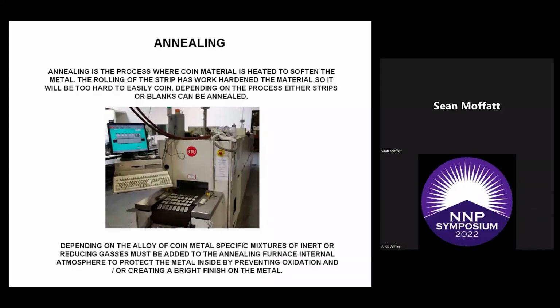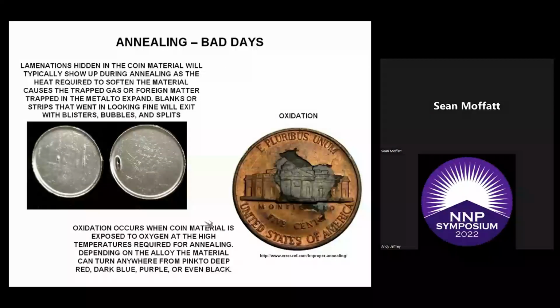All right, now depending on the process, you can either anneal your strips or the blanks can be annealed, depending on what you want. Now, depending on the alloy of the coin material, specific mixtures of an inert or what's known as a reducing gas must be added to the annealing furnace internal atmosphere to protect the metal inside by preventing oxidation and or creating a bright finish on the metal. Most commonly what's used is a nitrogen and hydrogen mix. The nitrogen pushes out any of the oxygen and the hydrogen burns off any that might be left in there, and it also helps create a bright finish on the blanks or the strips as they come out of the annealing furnace. But we have problems with annealing as well.